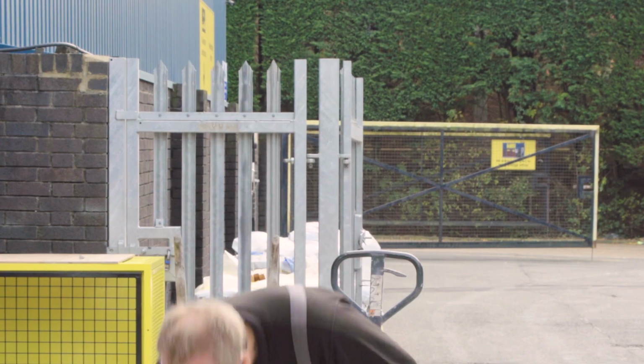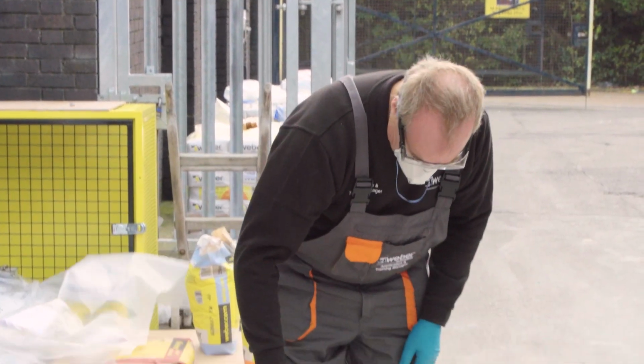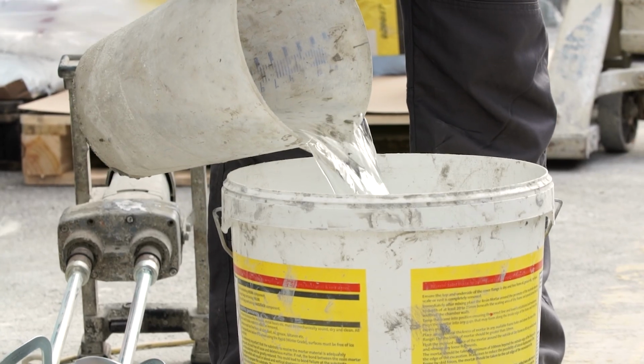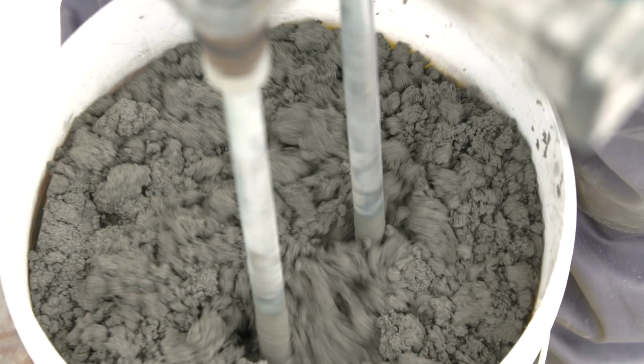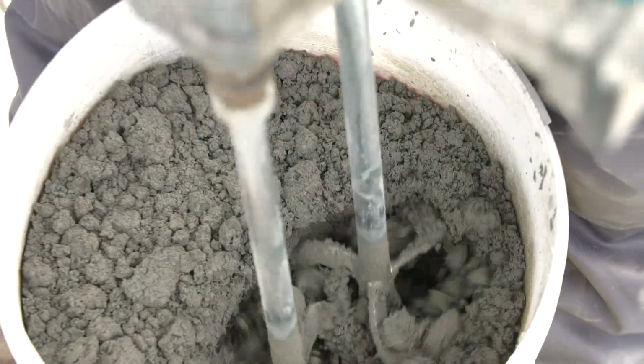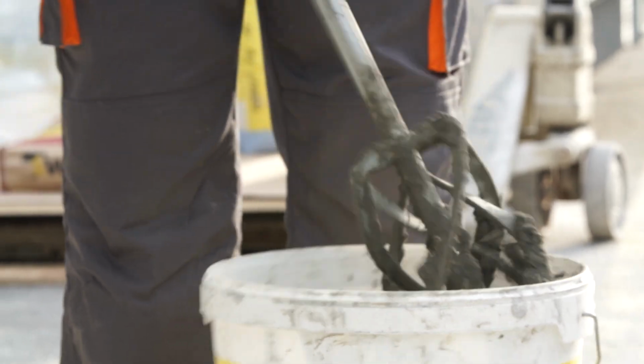Webercem HB30 needs to be mixed with between 2.4 and 2.7 litres of clean water per 20 kg bag. Pour the water into a bucket and insert the mixing paddle or blade. Open the bag and slowly add the powder to the water. Mix for 2 minutes from adding the powder to the water. Over-mixing will entrain air and reduce the compressive strength.